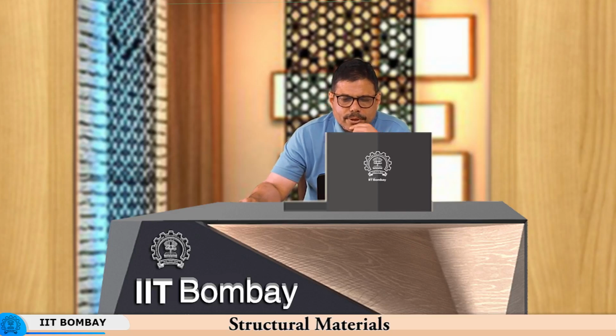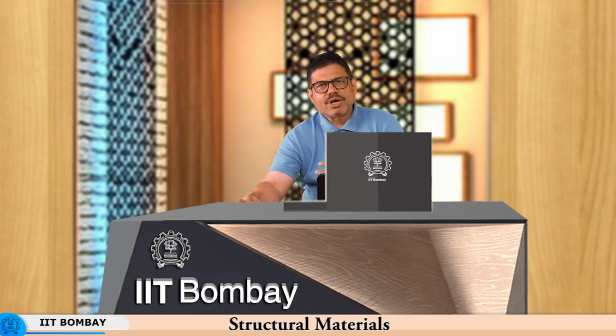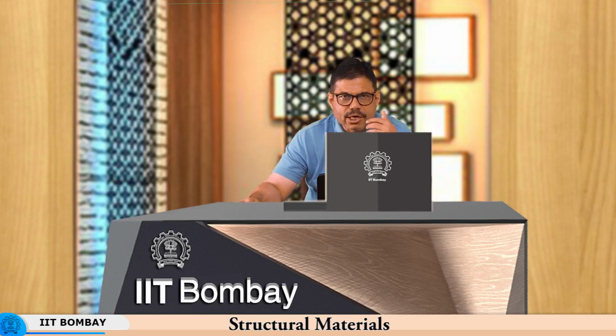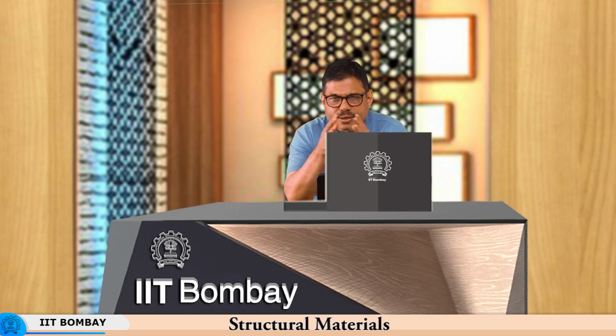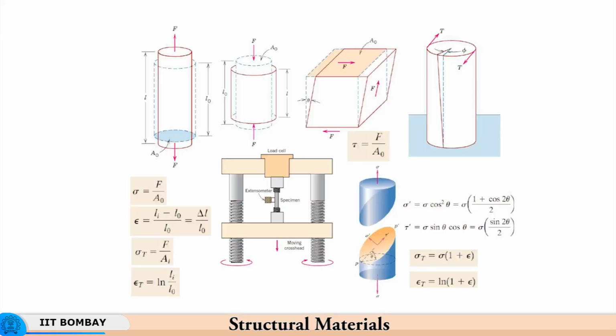When sin 2 theta is equal to 1, that is the maximum you can possibly have in terms of the shear stress, and this will happen when angle 2 theta is equal to pi by 2, which means theta has to be equal to pi by 4. So, when this angle is 45 degrees, you have the maximum shear stress. That is why you have the maximum shear stress theory when it comes to predicting plastic deformation. A structure is said to have failed if the structure undergoes plastic deformation.